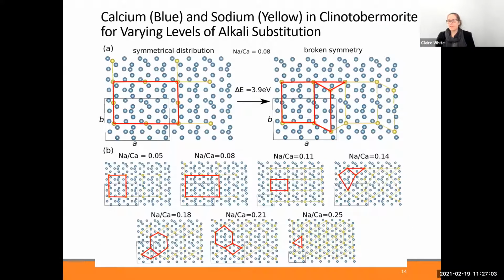What we found was kind of interesting. We found that it depends on the arrangement of the substitution as to whether there was an energy penalty for the substitution or not. So for example, here, if we're looking at a sodium to calcium ratio of the whole structure of 0.08, so some sodium has been incorporated for calcium, there's two different arrangements that you can get. Well, these are two that are shown.